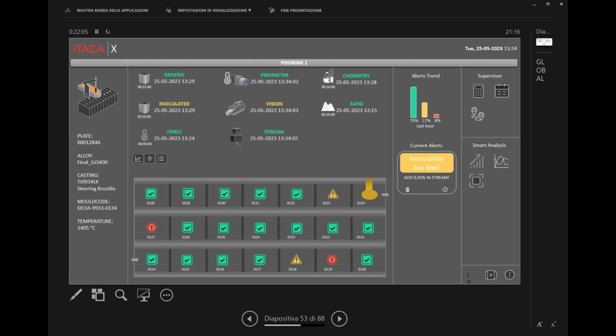Just understand that we started the process not from the equipment, but our know-how was mainly on the process. So we created the thermal analysis system, and later we developed the machine. This is very important because we created the equipment, the sensor, and the machine in order to solve the problems that we were facing in the process. A good example of the difference between these two approaches is the cementite. If any of you has a thermal analysis system, you know that you get the cementite when the eutectic temperature is lower than a specific value that you set for a casting.